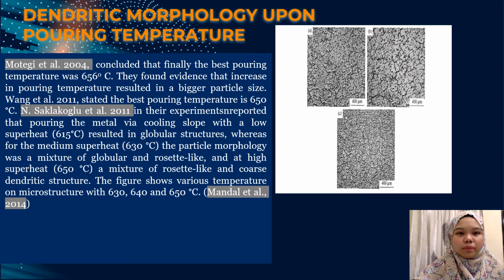Dendritic morphology upon pouring temperature. Motegi et al. 2004 concluded that the best pouring temperature was 656 degrees Celsius, and they found evidence that an increase in pouring temperature resulted in a bigger particle size. Wang et al. 2011 also stated the best pouring temperature is 650 degrees Celsius.